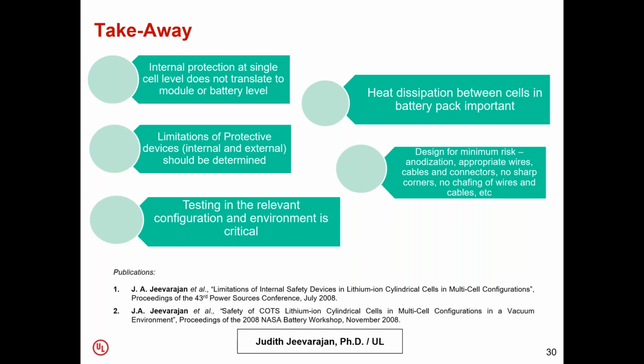Heat dissipation between the cells is quite important. We have seen that in this particular case that I showed, we saw a lot of charring and electrolyte leakage, but we didn't see a big fire. But when we tested the same string in a vacuum environment, we found that the cells go into catastrophic thermal runaway with a big fire. And so you just need to test it in the right environment.